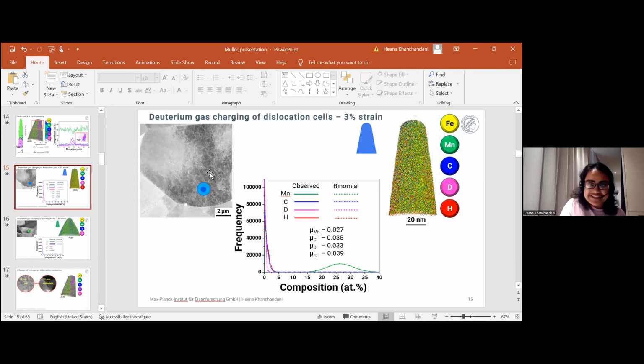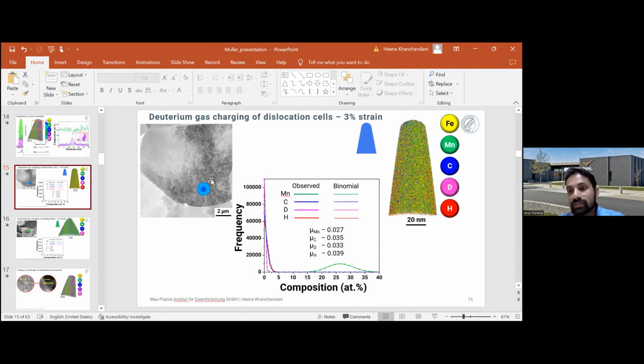So I was expecting that there should be some dislocation in the tip, but there is no segregation. So that simply means that maybe it is segregated at an entire cell, but if the cell wall is broken, then there is no segregation at the dislocation itself. So yeah, there are several reasons for this in this material itself. Okay, great.